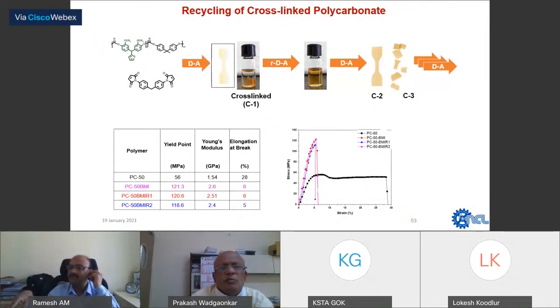And more importantly, it's not a simple bisphenol, but a bisphenol with a pendant furyl group, which is capable of undergoing click reaction, and this has come into prominence because you can convert this thermoplastic into thermosetting, which is a thermally reversible kind of reaction, meaning you can increase the mechanical properties of this thermoplastic and then recycle it, simply by heating at 130 or 140 degrees centigrade, where this retro Diels-Alder reaction takes place.